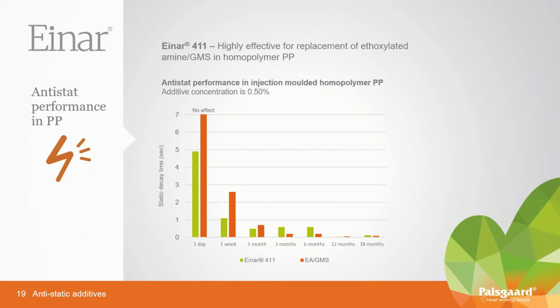We are comparing to a very well-known and used combination anti-stat-wise in polypropylene, and that's ethoxylated amine and GMS. We are seeing that some of those chemistry that traditionally has been used as anti-stats in many different food packaging applications are changing, and there's an increased focus on not using the ethoxylated amine chemistry due to safety, and so it's questioned whether it's a good idea to use those kind of materials that migrate to the surface and potentially can migrate into food.